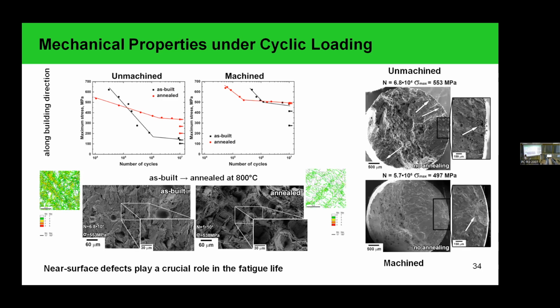But back to the machined samples, as I said, the main contributor to the fatigue life is the formation of near-surface defects. And here I would like to highlight that at near-surface zones, the volume of the defects is higher in comparison with the inner printed material. So it is essential to adjust the scanning strategy, or just remove these defects, to increase the fatigue life of the material.